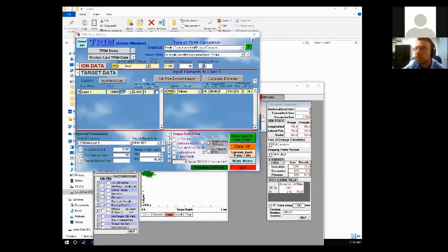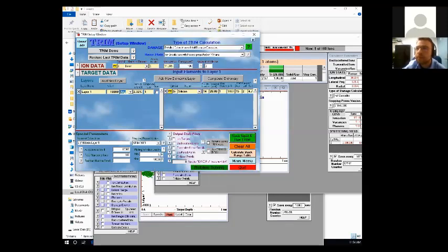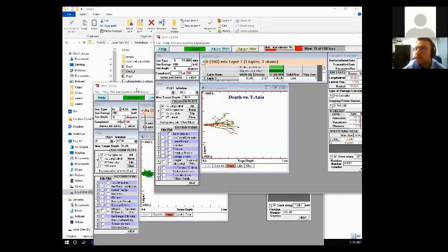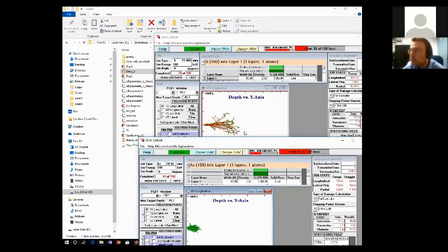Yes. So this is the drastic importance. What is so different between the two? Okay. I hope you guys can see the difference clearly. Boron is only giving us the damage towards the end of its range, towards the stopping point. When it loses energy, then it starts to interact with the crystal all of a sudden.